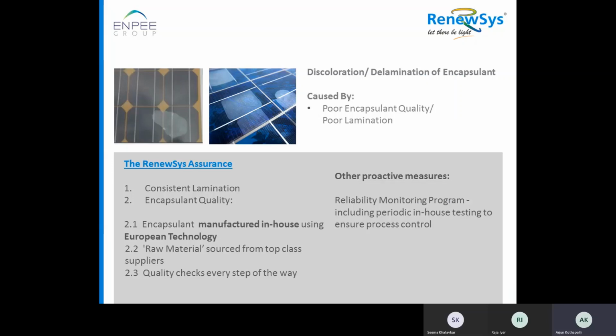The first is discolorization or delamination of EVA. This happens because of poor encapsulant quality used in the module or a poor lamination process. In RenewSys, as you know, we manufacture EVA, so the total quality of EVA is in our hand. We control total quality, and we manufacture modules as well. We manufacture solar cells, and we manufacture backsheet. So all the critical components in the module are manufactured by RenewSys. We have total quality control on the complete process.